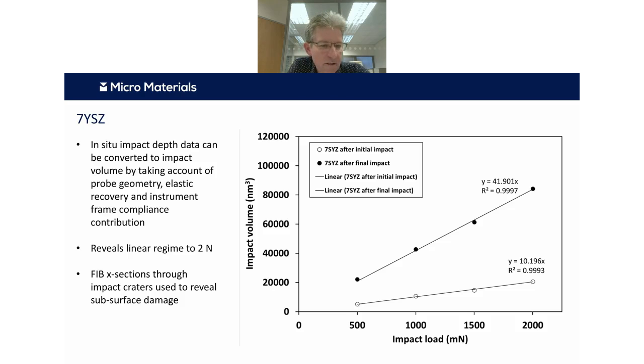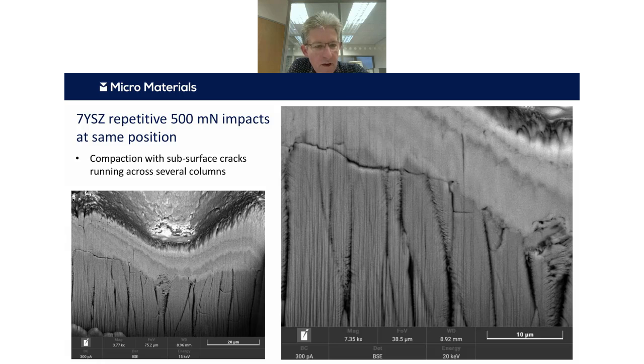The next step was to look at focused ion beam cross sections through these craters to look at the subsurface damage and see how that compares with erosion. This is an example of one of the impact craters at the lowest load we looked at, which is 500 millinewtons. We can immediately see a compaction zone in the center of the crater, and just below that compacted area a lot of cracking going across these columns. In some cases this cracking is being stopped or deflected by the columns, and this is one of the things leading to material removal.